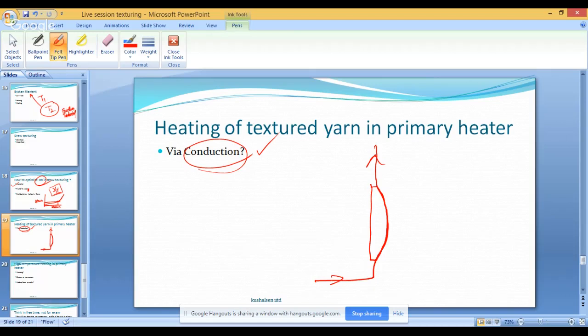Some findings later established that conduction may not be the mode of heat transfer. Because in a textured yarn situation, the yarn is not just moving over the heater plate, but it is rotating, and rotating at a very, very high speed. That would mean that around this yarn, there is almost a layer of air which is swirling along with it.